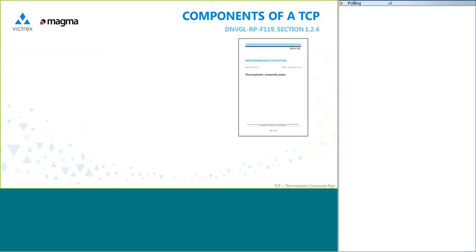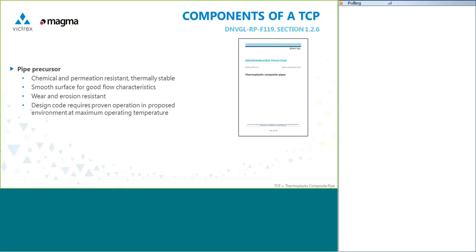These are described in a recently finalized document by DNV GL. It's a recommended practice, F119. And that recommended practice describes the parts, the component parts, the function, the design, the testing, and the qualification of a TCP. It's set out all in that document, and it is downloadable from the DNV site. Now, the DNV document describes basically a pipe precursor for a thermoplastic composite pipe.